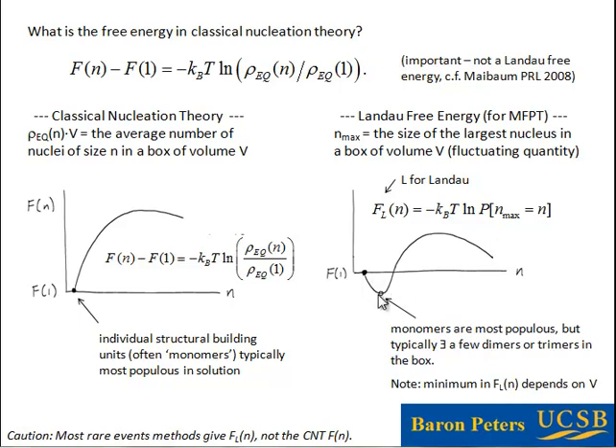If you have a very large simulation box, the minimum will shift further to the right, because spontaneous formation of trimers or tetramers becomes probable. So this Landau free energy curve depends on the volume of the simulation box — it has a very different shape. But that's okay because it has a different meaning, and in the theories where we use it, it will give the exact same rate as the framework where we compute the rate from the classical nucleation theory definition. The difference in physical interpretations is the guiding principle for building a theory that generates the correct rate.